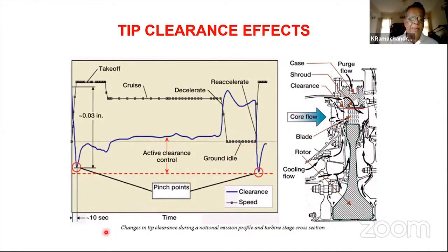And if you look at the way the engine, this is not an industrial gas turbine, which keeps running at the same speed for a very, very long time. And therefore, if you really do a good estimate of the gaps between rotating parts and the static parts, you can have, even while takeoff, a pinch point where there's a possibility of rub. And similarly, when you do a lot of throttle excursion, there are possibilities of rub, but more importantly, there are possibilities of gap widening, which affects the performance of the engine, which affects the efficiency of the parts.